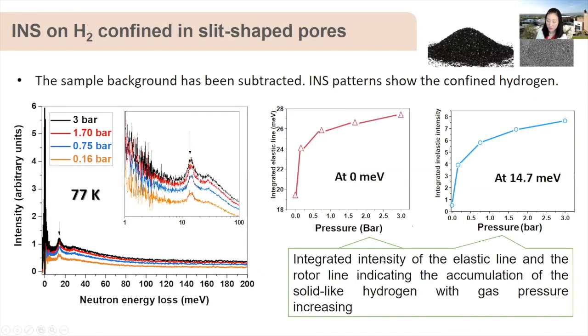Then, following a similar procedure, we load our sample, the activated carbon, that is pure carbon, there are no functional groups, no metal and no catalyst inside, just 100% pure carbon. We loaded the sample in the sample cell, and we cooled down the whole system to 77 Kelvin this time, and then pressurized the system with hydrogen at different pressures. And then we collected the data, and we found a solid-like hydrogen peak at 77 Kelvin at a pressure as low as 0.16 bar.